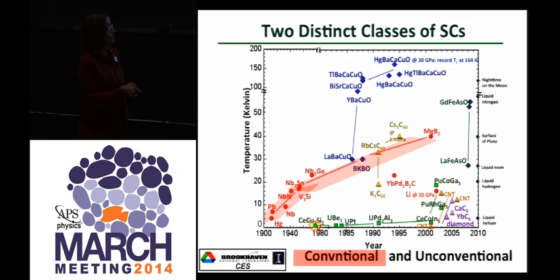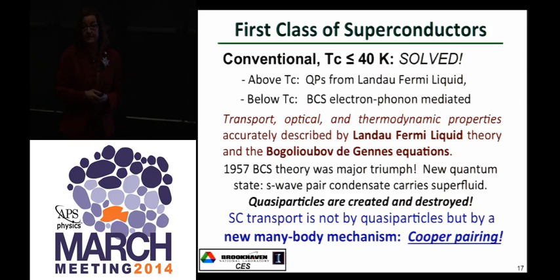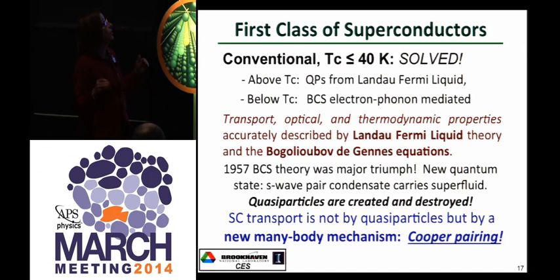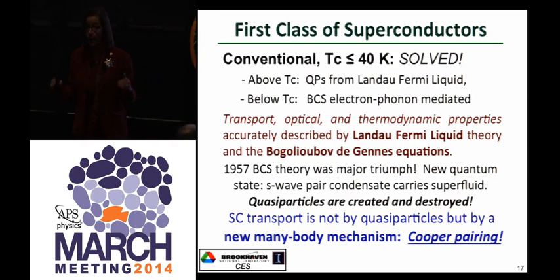And I put that little explosion here, that's where I think this started, because all of the other superconductors have a very similar phase diagram. So let's say something about these classes. The first class is what I'm calling conventional. The Tc is typically less than 40 kelvin, magnesium diboride. Above Tc, the transport is described by quasi-particles coming from a Landau Fermi liquid. We understand that. Below Tc, we understand that it's BCS electron-phonon coupling mediated to do the Cooper pairing. We understand that too. We can describe these states through Landau Fermi liquid theory and the Bogoliubov-de Gennes equations. We can't predict Tc, but we can describe these states.